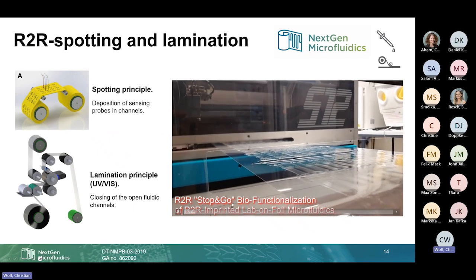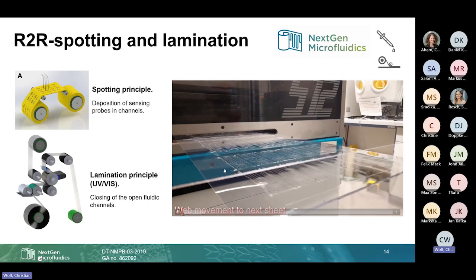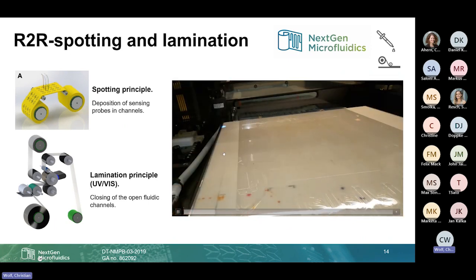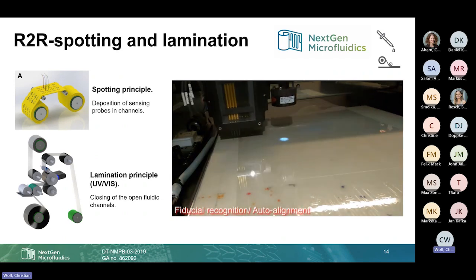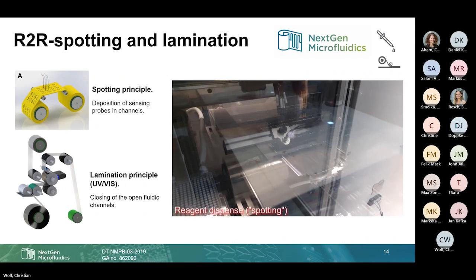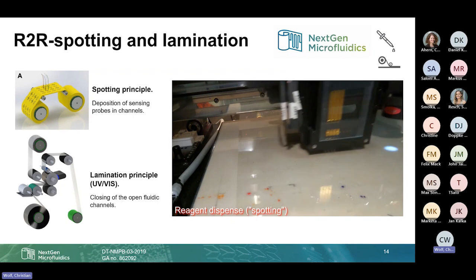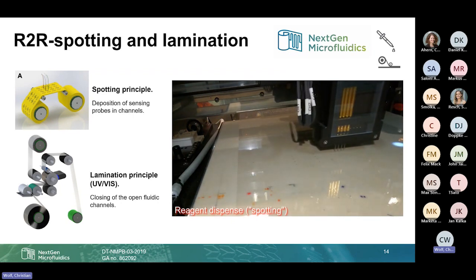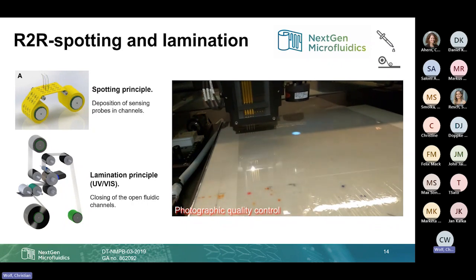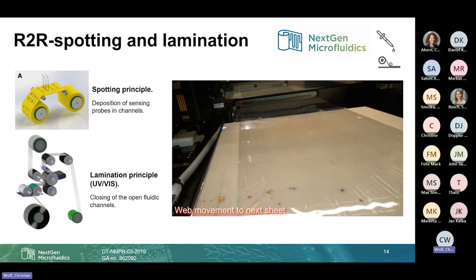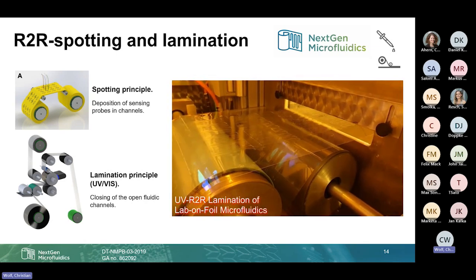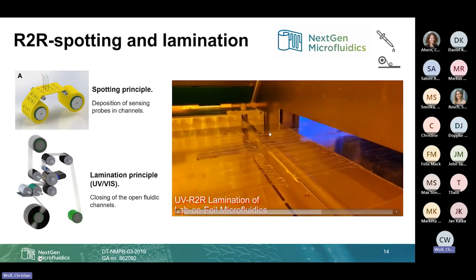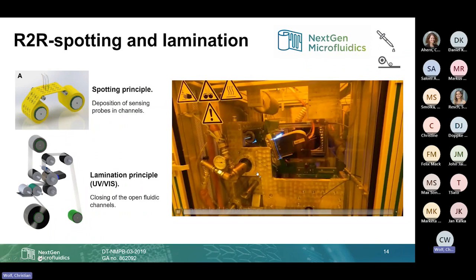So up to now, it's still in a stop and go mode. The spotting is done, but that can be further improved in a continuous process. But we can see here the web is transported into the dispenser, and after a short alignment, you can see how the biomolecules, the chemistry, the markers are spotted into the channel automatically. So we are just using 4 nozzles for this process. This can be scaled up, of course, by using more nozzles in parallel. So after spotting and a quick quality control, the web moves on to the next sheet, and then the next chips can be spotted. And here you can see a short video of the roll-to-roll lamination process, where you close the chips with a cover foil.